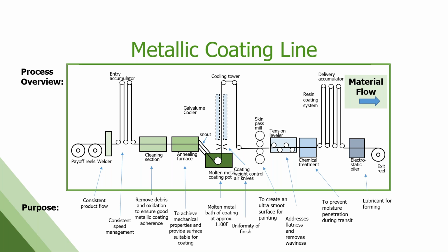You've got to get that raw steel clean, get all the oxidation and rust and stuff off the surface. Then it would go through an annealing furnace, a direct fire furnace. Normally, you're actually heating the strip up with flame. This is, again, cleaning the strip so that you can put your metallic coating on it. It's also annealing the steel, so you can get whatever grade of steel you need, whether tensile strength or yield strength you need for the final product. That occurs in that section.